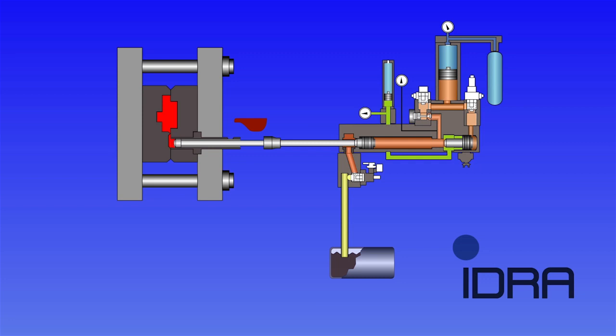The movement of the intensification piston must be controlled in two ways. First, the stroke of the piston regulates the final pressure applied to the metal inside the cavity of the die. This is dependent on the projected area of the casting and the desired results required. Typically, pressure tested castings may require up to 900 bar of applied pressure to ensure that there are no leaks from the component.